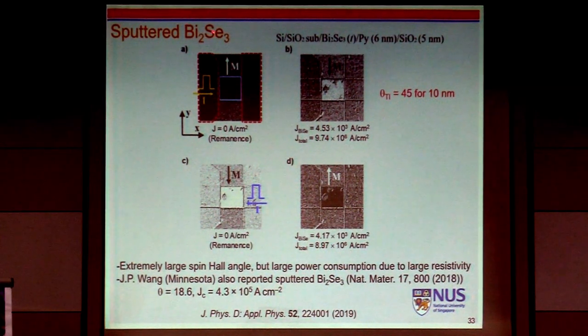So we sputtered this bismuth selenide in a conventional sputter machine, purchased this sputter target. Then we sputtered about 10 nanometer bismuth selenide. We can show a similar effect. We injected current, the magnetization flipped from here to here. And here we apply the current from the right electrode, we can flip.